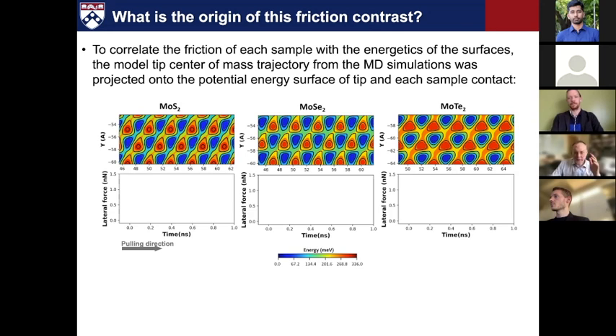A very good question. The stresses and thus the strains can be quite high under this very small AFM tip. If you have the layer supported on a substrate, then you're compressing. If it's a suspended membrane, actually, you'll be pushing down that membrane and you can stretch it and get quite a bit of tension there. So we haven't looked at that, but I have seen a couple papers where other groups have reported that the forces applied by the tip can induce changes in the electrical properties. And particularly there's this 2H to 1T transformation that can occur in these TMDs.